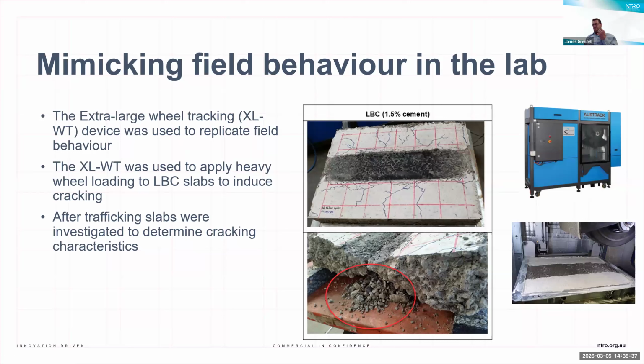We tried to mimic the behavior in the laboratory, again using the extra large wheel tracking device, so that we could understand a bit more about its characteristics and how it would perform, or that shift between laboratory performance and field performance. Again, you can see that under traffic loading, it starts to break down almost into a granular material. This is looking at the slab afterwards. After testing, it doesn't seemingly really break down into block cracks, but under the wheel path, the material's broken down into an unbound granular material.